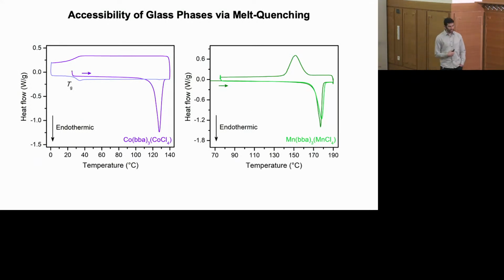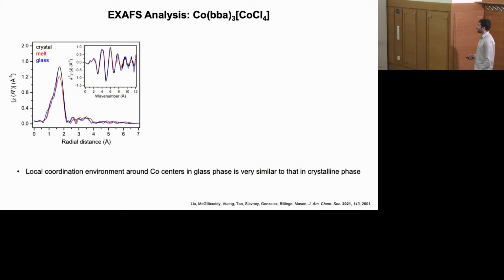I'll just highlight that these materials offer access to a wide range of different glassy phases through melt quenching reactions. So if we take these materials, induce the melting transition, and quench them at relatively quick rates, we can undergo transitions to form a glass. Certain other materials will recrystallize very quickly, and it can be very difficult to access a glass phase. So we've spent a fair bit of time trying to understand how we can tailor these materials to tune the kinetics of these crystallization versus glass transitions.